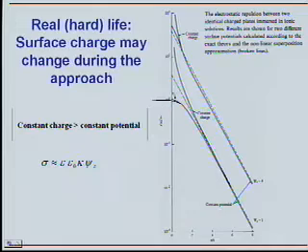Now imagine, however, that you put some surfactant on the surface and the surfactant doesn't stick very strongly to the surface. If you bring the two surfaces too close, the surfactant is going to be uncomfortable there, so it's going to start dissolving and moving away from the surfaces. Beyond a certain threshold, the surfactant is really going to start leaving the gap between the particles. So that's why the force is going to be smaller than the force that you would expect theoretically. Or otherwise the force is going to be stronger, because the potentials overlap so much that no linear approximation is valid. You have highly nonlinear, strong electrostatic repulsion.